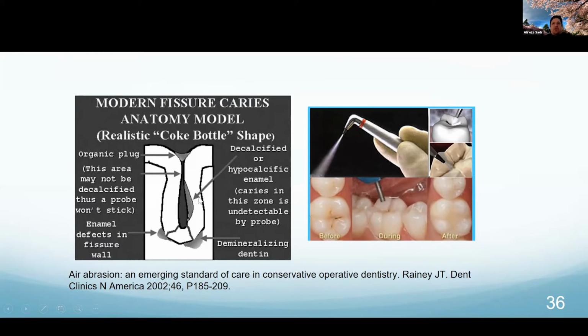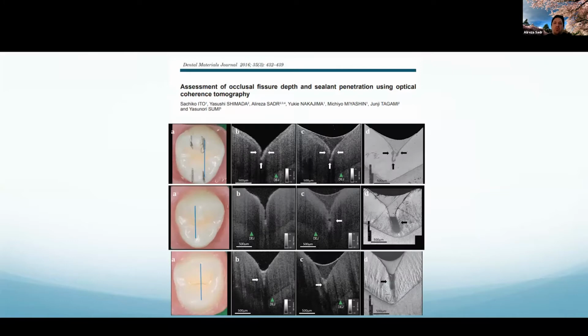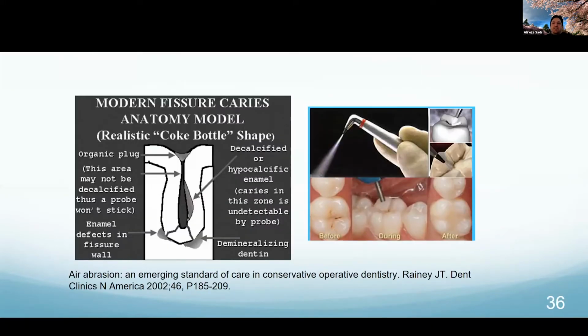So I want to open a parenthesis here. Air abrasion for sealants is probably a must, right? You look at minimally invasive dentistry, based on what we found with OCT, where it's very difficult to get a complete penetration into the fissure. It creates a very good tool and a very good modality for us to be able to open the fissure. So talking about that toolbox, we talked about bioactive desensitizers. The next thing a modern dentist want to have in their practice, if you don't have already, is some sort of air abrasion, micro etcher, whatever brand that there's AquaCare out there that has water flow as well. So all of these are great. You should have a precise tip to be able to kind of control your air abrasion and open up the fissures for a complete and successful penetration of the sealant.